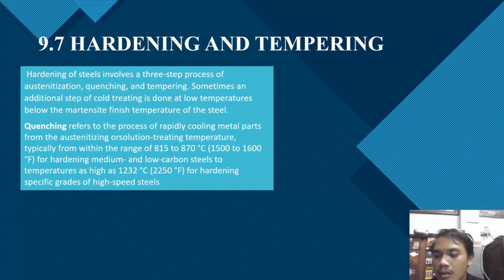Quenching refers to the process of rapidly cooling metal parts from the austenitizing or solution treating temperature, typically from within the range of 815 to 870 degrees Celsius, which is 1500 to 1600 degrees Fahrenheit, for hardening medium and low carbon steel, to temperatures as high as 1232 degrees Celsius, which is 2250 degrees Fahrenheit, for hardening specific grades of high-speed steel.